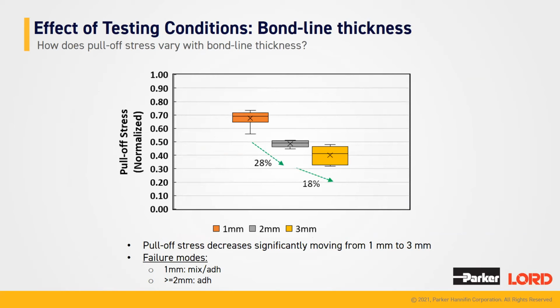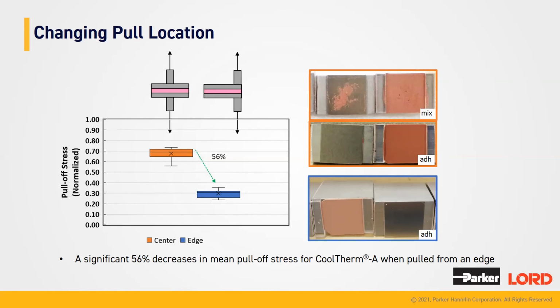Moving to bond line thickness, there actually is a statistically significant decrease in pull-off stress, moving from 1 millimeter to 2 millimeters and from 2 millimeters to 3 millimeters. In this testing, the 1 millimeter samples had mixed and adhesive failure, whereas anything greater than 2 millimeters had all adhesive failure.